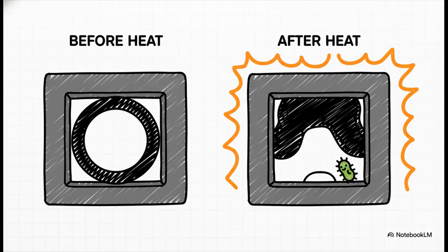So an absolutely crucial point here is avoiding what I like to call the thermal expansion trap. Engineers will often try to improve cleanability by installing elastomers, like O-rings, into extremely tight grooves. Makes sense on paper, right? But elastomers expand significantly faster than stainless steel when exposed to heat, so during a hot washdown cycle, that tight O-ring suffers from chemical swell and thermal expansion. It literally extrudes right out of its groove, creating the exact crevice you were trying to avoid in the first place.